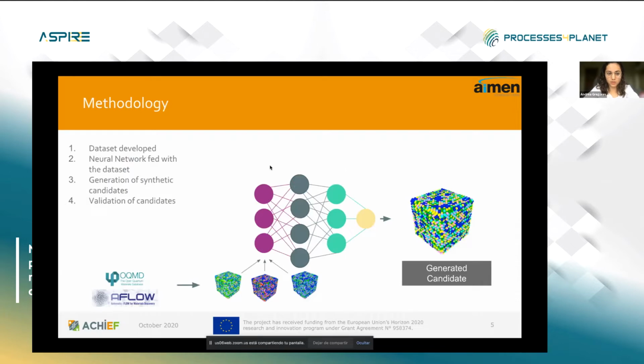So the methodology was as follows. First of all, a dataset was created based on literature. Once this dataset was finished, it was used to feed the neural network, and we trained the neural network with this dataset. Once the neural network was correctly trained, it was able to generate some candidates to be possible high entropy alloys. But in order to check if they could accomplish the properties of these concrete alloys, a validation method was developed. In this case, we have made use of databases based on density functional theory to check if they had the properties to be high entropy alloys.